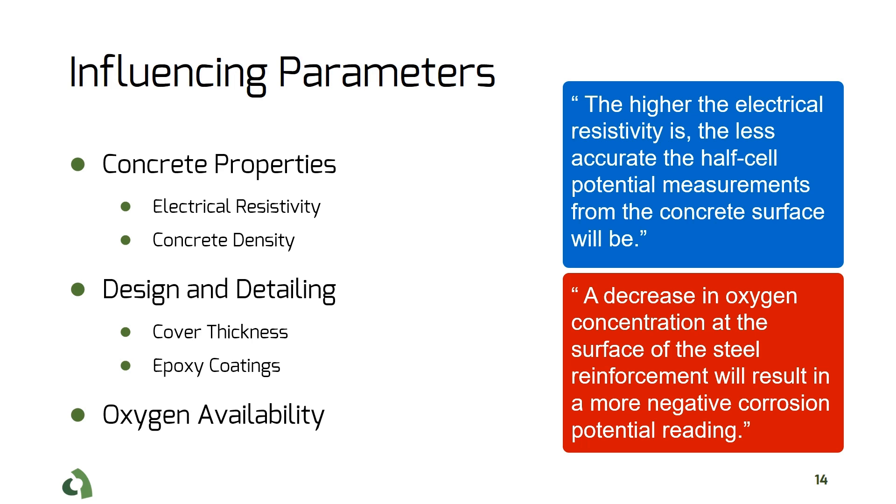Also, a decrease in oxygen concentration at the surface of the steel reinforcement for concrete in fully saturated conditions will result in a more negative corrosion potential reading.